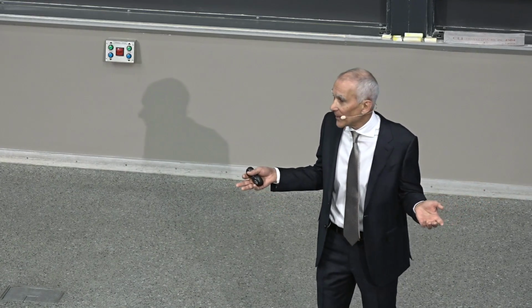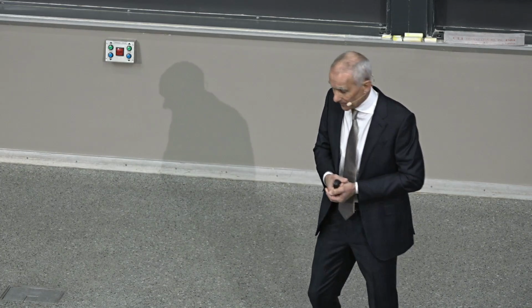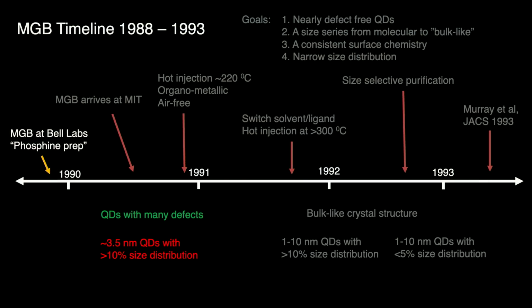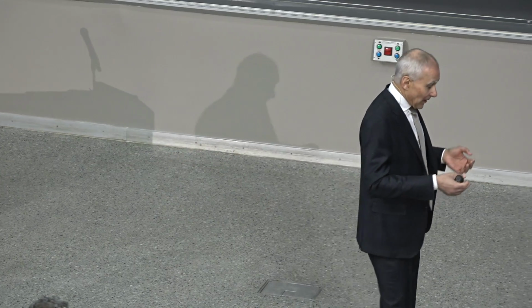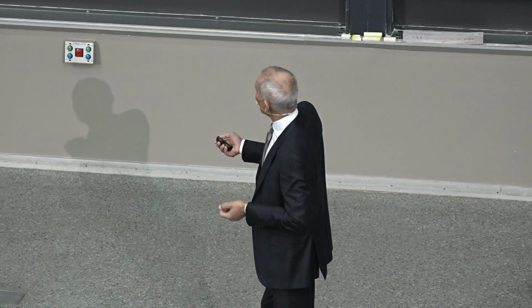Pretty much nothing interesting happened except for one bottle of tributylphosphine, which is a Lewis base that has a phosphorus atom there. And then I cooked it in, and I saw growth of the color from yellow to red, and the particles starting to emit light. Before that, we never saw light coming from the particles. They absorbed light, but they didn't emit. And wow, that was amazing. And I called that the phosphine prep.